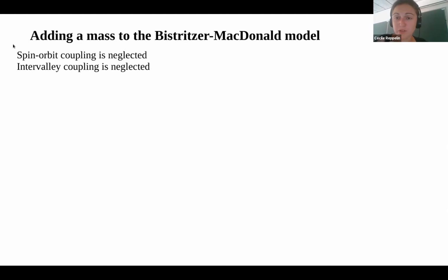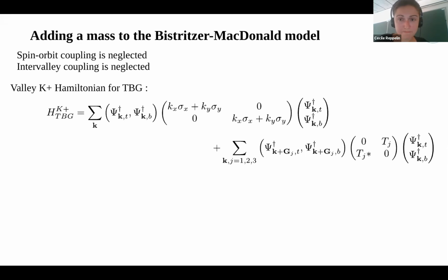Let me describe the model that we are using to describe the situation. As is the case for magic angle twisted bilayer graphene, we neglect spin-orbit coupling. It's extremely small. Intervalley coupling is also neglected in this model because it's exponentially suppressed. We start from the Bistritzer-MacDonald model. Again, this is just a reminder from what you did last week. We can separate valley K plus and valley K minus, however you want to call them. Valley plus corresponds to one chirality, and valley K minus is the time reversal partner of that valley. So we can write down the Bistritzer-MacDonald model in this one valley.